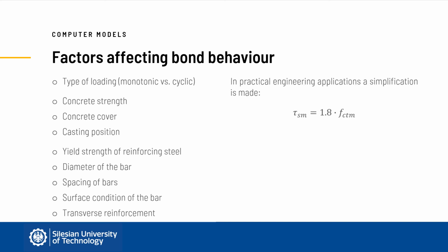In practical engineering applications, it is convenient to assume that the mean bond stress is independent of the crack width. In such applications, for example in design codes, the mean bond stress is represented in relation to the mean tensile strength of concrete. However, it must be remembered that bond stresses change with the slip, so while the crack develops, and it is important to account for this fact in the model to obtain realistic results.